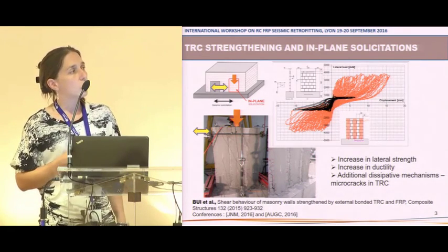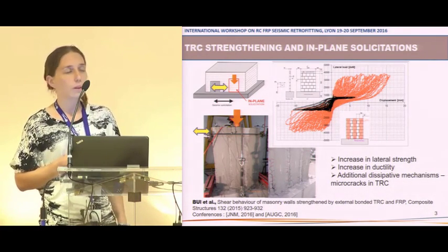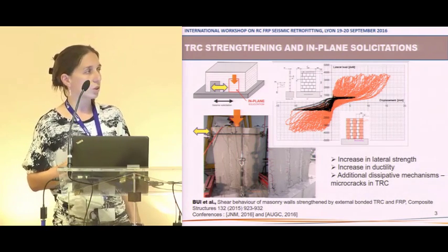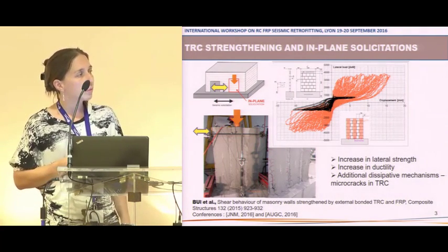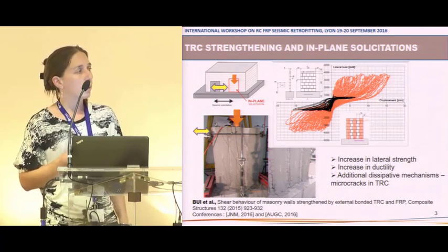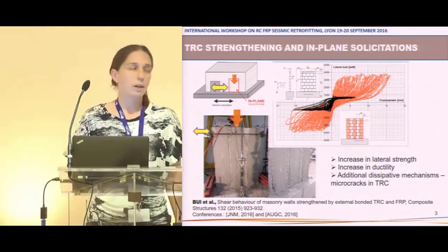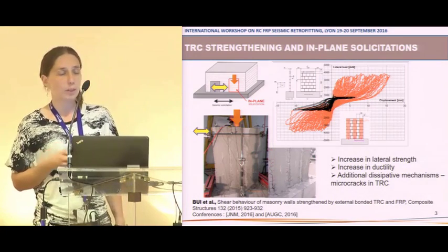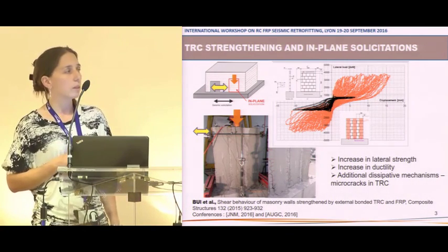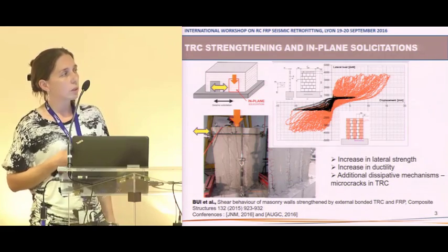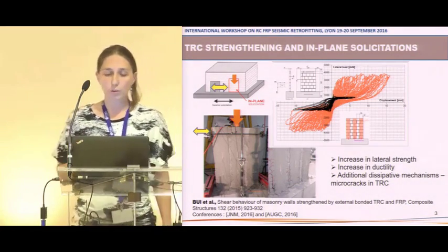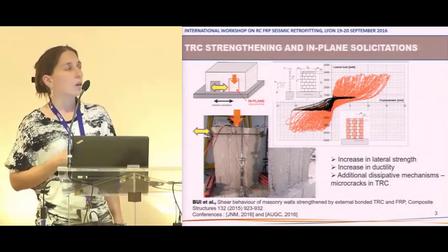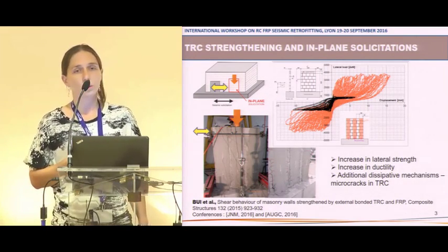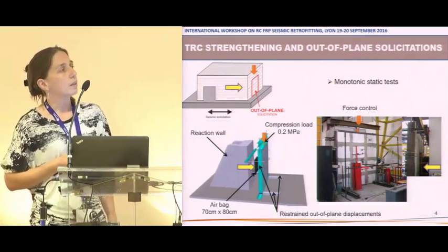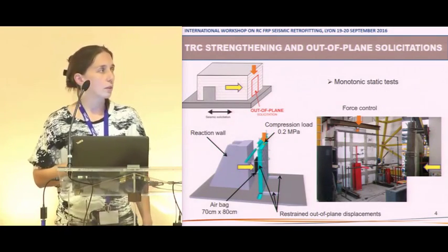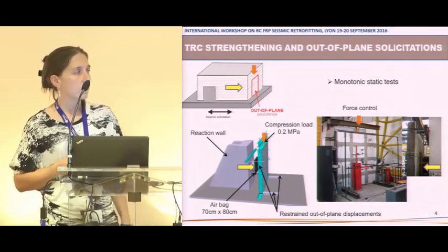masonry walls. And it appears that the reinforced walls have a good ductility and a good energy dissipation, because the cracking behavior of TRC provides an additional dissipative mechanism compared to FRP, which can be interesting at the ultimate state. And as the experimental results were conclusive under in-plane solicitation, we have decided to continue with the study under out-of-plane solicitation. And with this in mind, we have designed the following test setup.